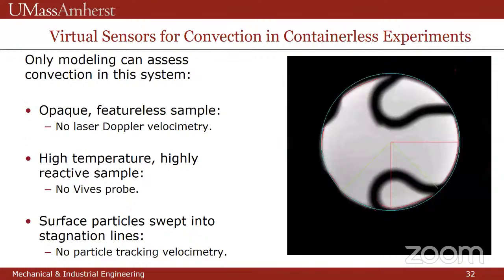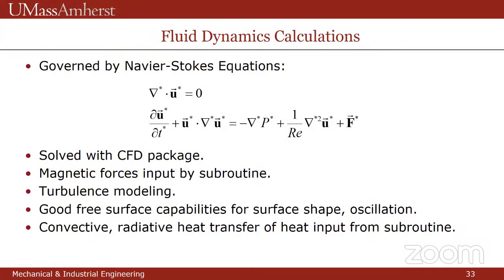So in this system, we have an opaque featureless sample, so you can't use a lot of the methods you'd like, no laser Doppler velocimetry or particle tracking. The sample is high temperature and highly reactive, so you can't put a magnet in it to use a probe. And if you do have a composition where you can put particles on the surface, and we do sometimes, those get swept into the stagnation line, so they don't tell you much about the fluid flow anyway. So the fluid dynamics is governed by the Navier-Stokes equations, and there's some details here.